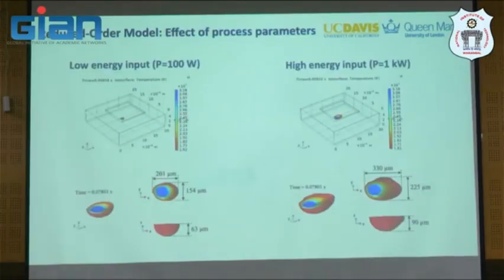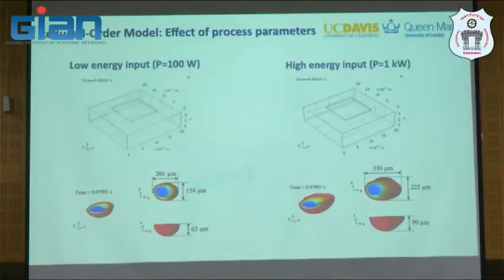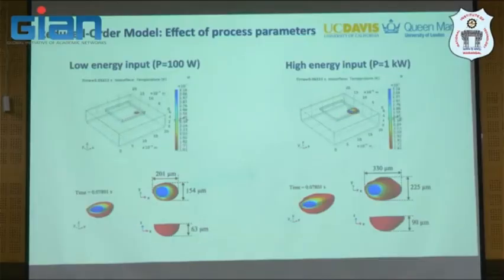And if we try to make this more predictive, we try to calibrate now with available data. You see that we use a quite small mesh size here, and you see the melt pool here is actually in the size of 150 to 200 micron. And if you go back to the literature, from SEM, TEM, or optical microscope, this is the size of the melt pool that we see in the experiment as well. So this is the dream that we want to have, quick, but not very quick I would say, at the moment, with just a single laptop or workstation that we work on here, that we can capture some of the things that are probably similar to experimental data. But this is one attempt that we try to study the dependency of the property.